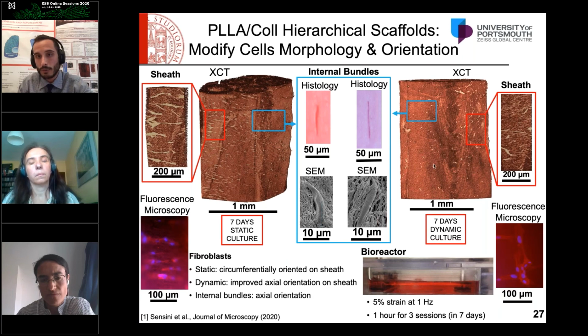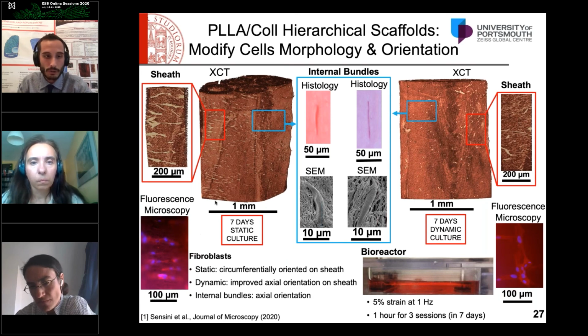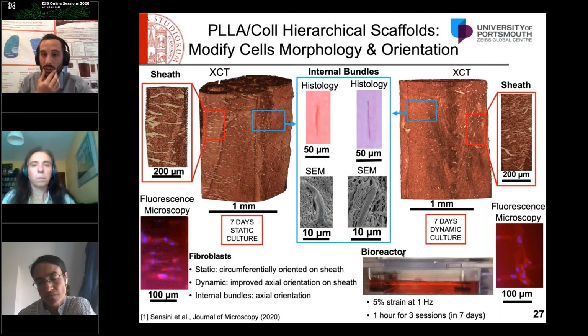After the cyclic test, what is very interesting is that the membrane is very able to transmit the axial loading of the testing machine, transmitting this preferential axial load onto the cells. As you can see here, after the cyclic loadings, the cells are able to completely change their shape and start to align with the scaffold.